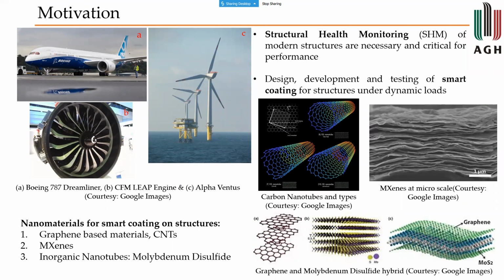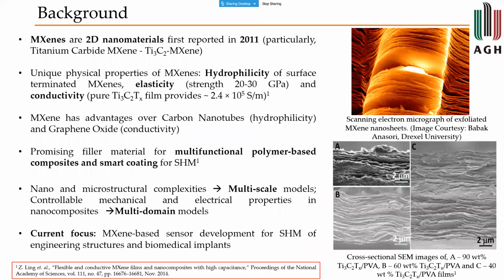and graphene. We were looking at materials that can be well processed and used for these coatings, and MXenes was one of the options that we found could be promising for sensor development and also for use in structural health monitoring applications. So going forward, to give you a small background of what MXenes are: it's a family of two-dimensional nanomaterials. The first reported MXene was the titanium carbide MXene, which is very good with hydrophilic behavior, and that actually propelled its growth in the last 10 years.